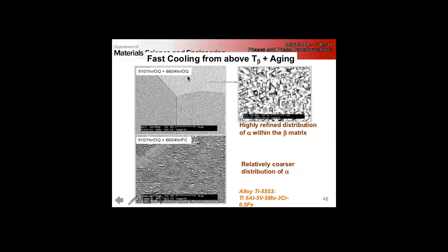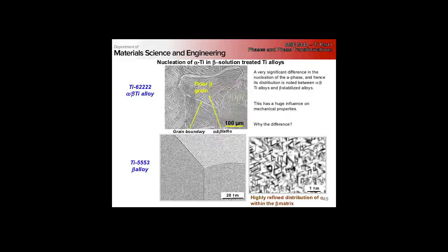Right, we get a very fine dispersion of alpha. You can see the platelets. If we do the same thing and then furnace cool, we still have alpha, it's finer, much finer than if we were to furnace cool from the transus. But it's relatively coarser, right? And if we take a look at a comparison between the alpha plus beta alloys and beta alloys, right?